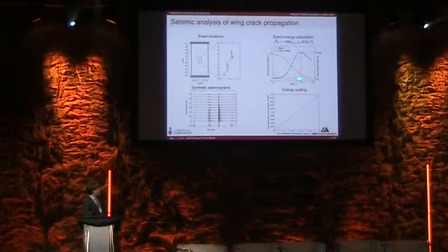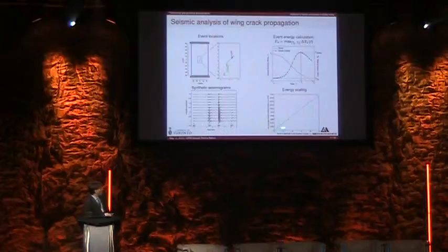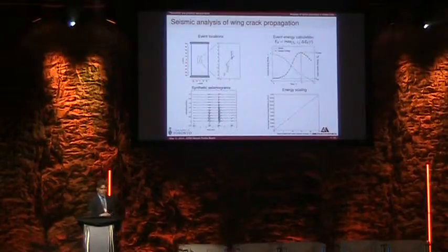We also developed a method to quantify the energy released by the fracturing process by monitoring the kinetic energy of nodes around the crack, the nucleating and propagating crack. And that energy was verified to scale with the actual energy that is recorded far away from the source.